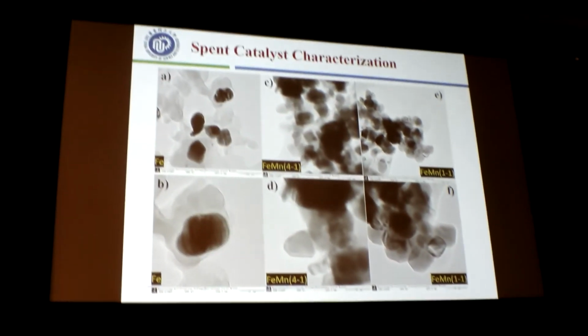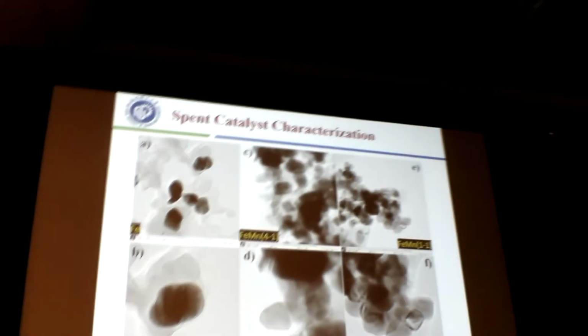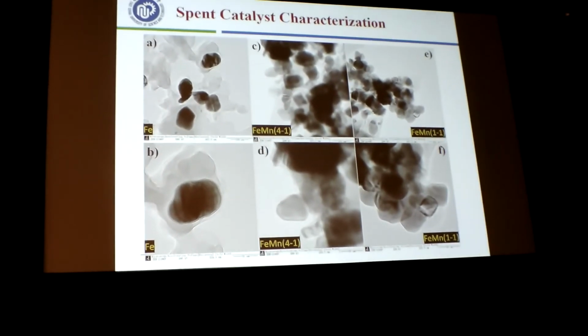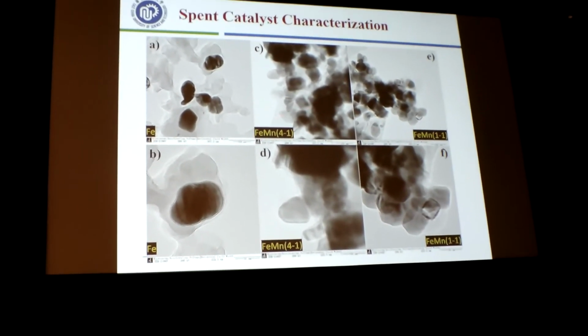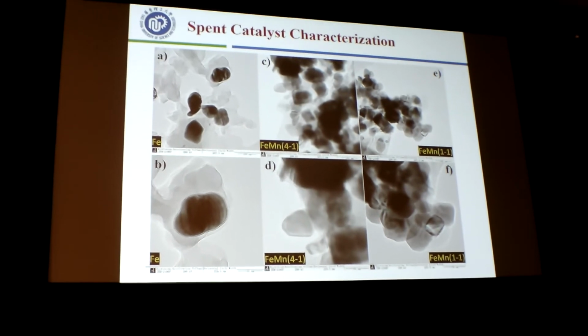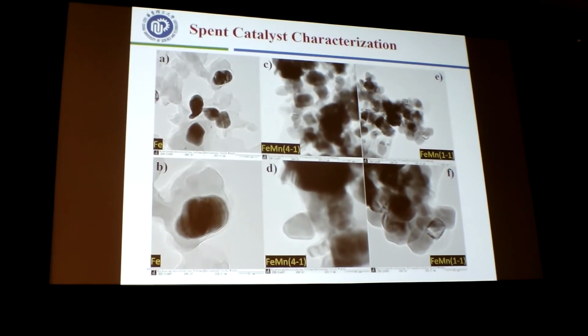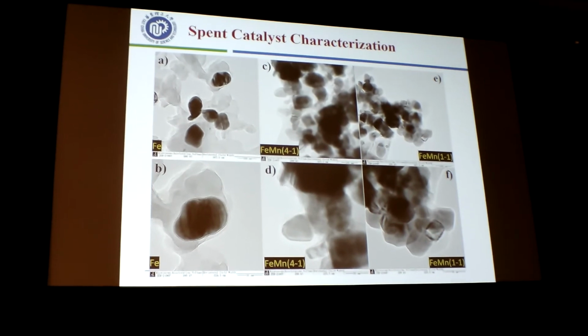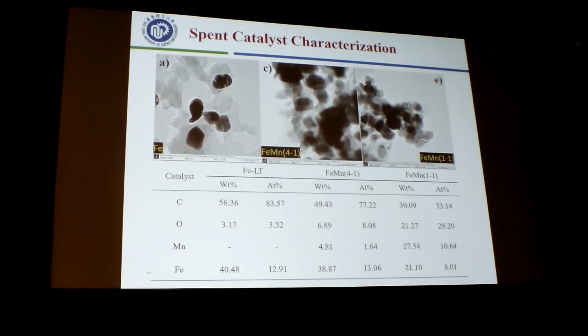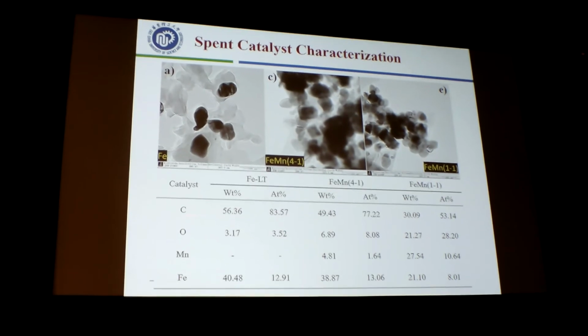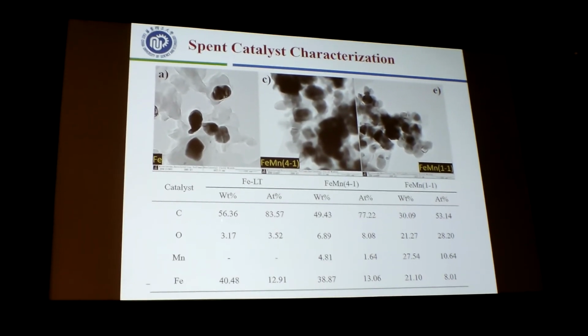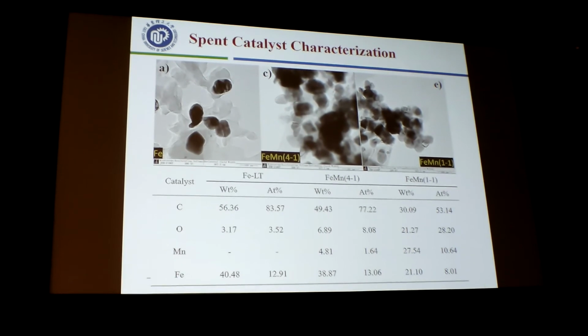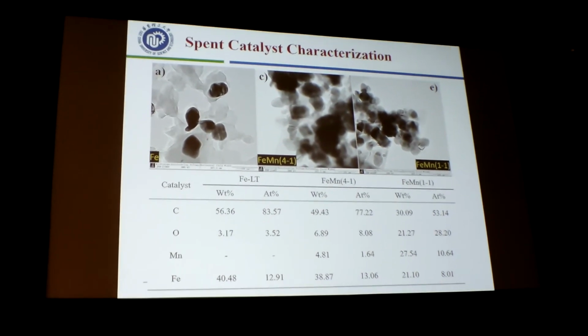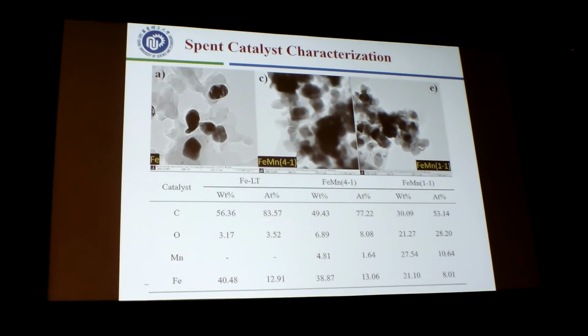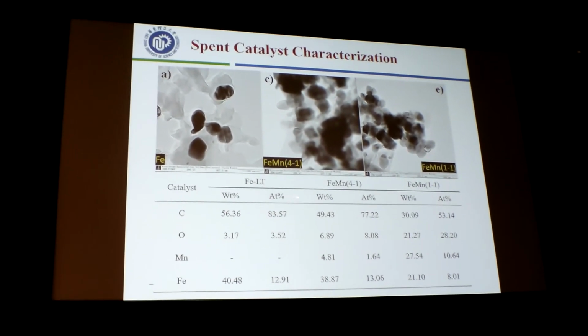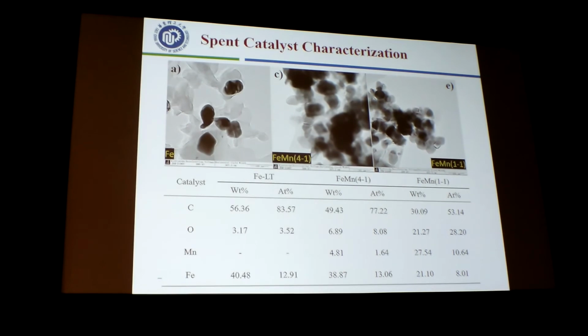So this is the TEM pictures of the spent catalyst. We can see the particle sizes are bigger than the fresh catalyst, and we also did the surface elemental analysis showing the deposition of carbon on the surface, but the catalyst which is doped with manganese have less carbon deposition than the single iron catalyst.